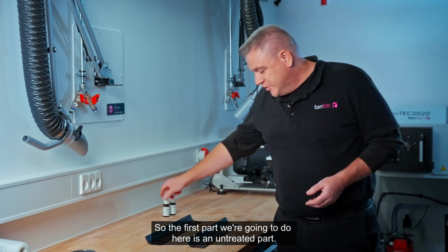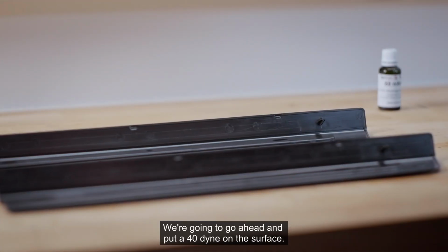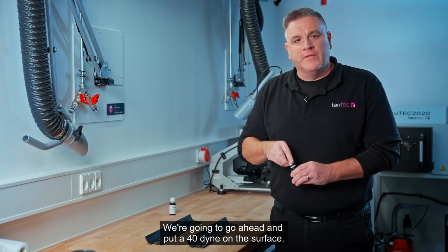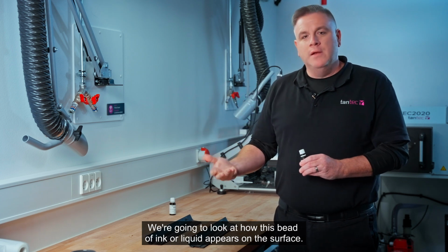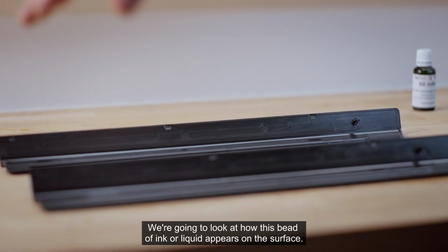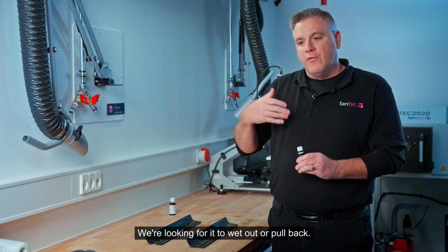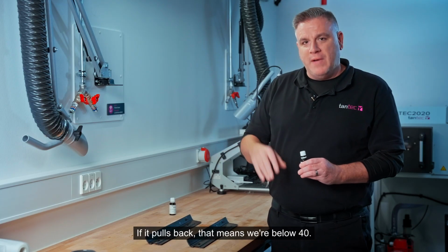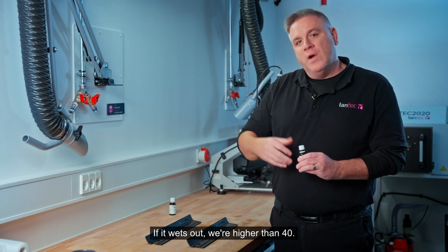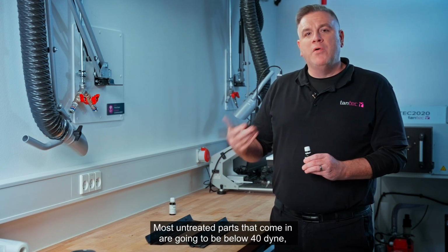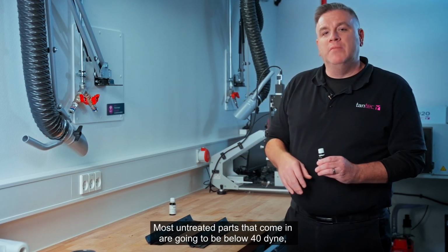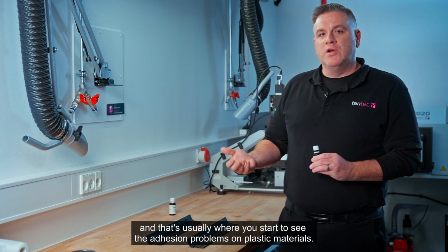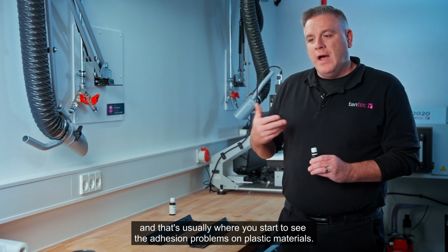So the first part we're going to do here is an untreated part. We're going to put a 40 dyne on the surface. We're going to look at how this bead of ink or liquid appears on the surface. We're looking for it to wet out or pull back. If it pulls back, that means we're below 40. If it wets out, we're higher than 40. Most untreated parts that come in are going to be below 40 dyne, and that's usually where you start to see the adhesion problems on plastic materials.